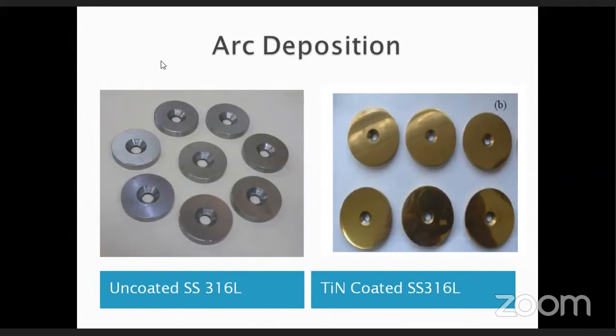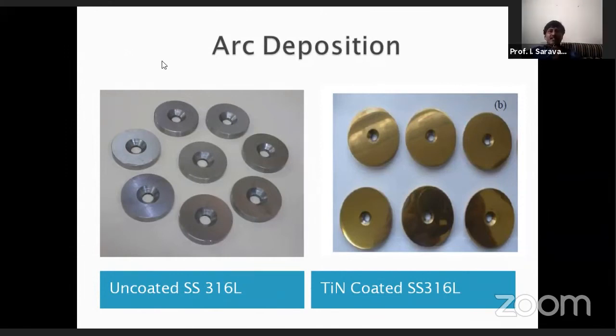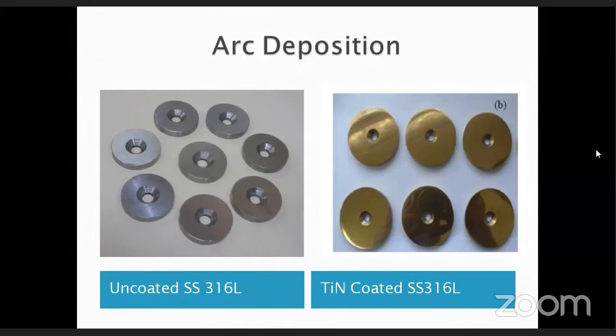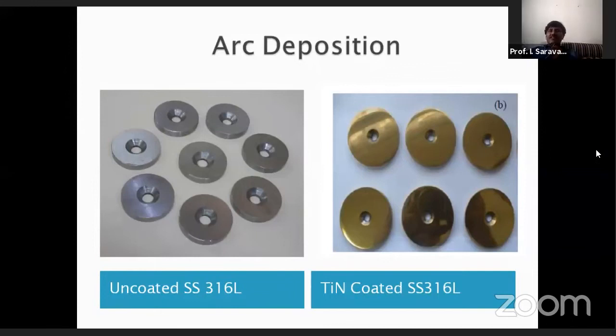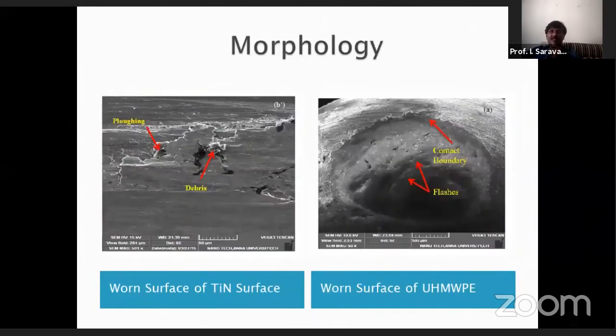The titanium nitride coating has been deposited by using cathodic arc deposition. This is around 8 micron thickness for wear resistance coatings. The adhesion strength is very good, and the hardness of the coating is around 1800 Vickers hardness. The micro hardness of stainless steel is generally around 230 Vickers hardness number. After the coating, it has improved around 8 times, and the surface roughness is also improved, in the microns level.